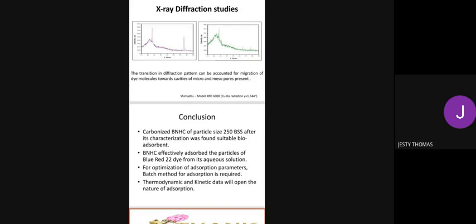We have not studied the desorption method, because the desorption parameter is included in the batch adsorption method. There we study the effect of adsorbent dose, contact time, and equilibrium time. All these parameters are studied in the batch adsorption method. Okay, then after it is adsorbed and desorbed, can you reuse the same material? If we see that there is successful desorption of the dye, then definitely, madam, we can use it for recycling purposes.